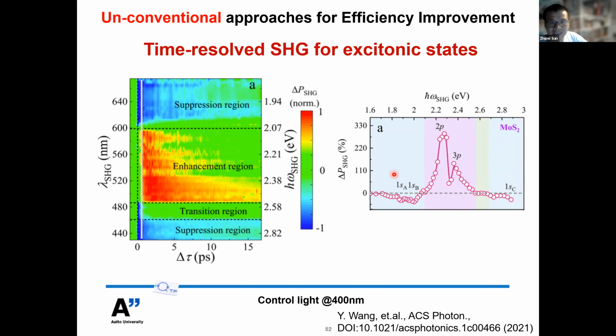So the results here show that this time-resolved second harmonic generation measurement not only provides an effective way to enhance the second harmonic generation, but also provides a very useful method to probe the excitonic states inside of the MoS2, inside of the 2D materials.